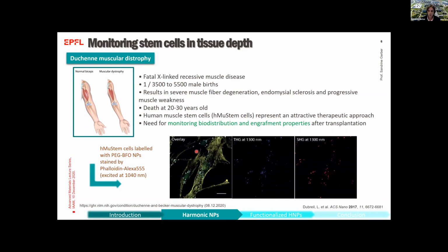Then we incubated hMuStem cells with those nanoparticles at a concentration of about 12.5 micrograms per milliliter of solution. Excitation at both 1040 nanometers and 1300 nanometers allowed imaging of the harmonic nanoparticles in all channels, as you can see here, and also clearly distinguished those nanoparticles from the background signals from the cells, which were at the same time stained with phalloidin Alexa 555 dye.